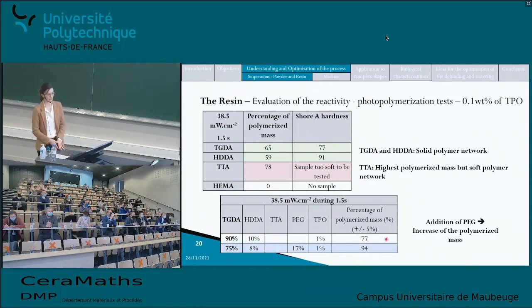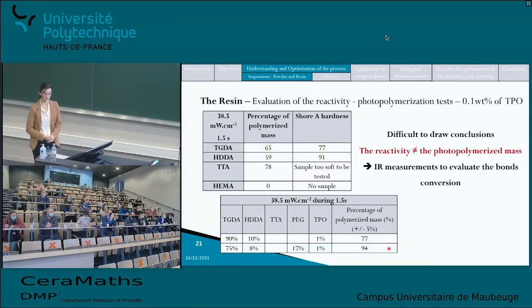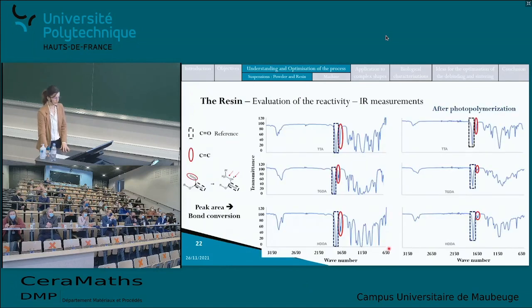However, it is difficult to draw conclusions with this experiment because the reactivity is not exactly equal to the photopolymerized mass. So I added some IR measurements to evaluate the bond conversion and to understand better what happens during the photopolymerization reaction. So I did the IR measurement on 3 of the monomers, the TTA, the TGDA, and the HDDA. So I did some IR spectrum before the photopolymerization and after the photopolymerization. And I evaluated the peak area on 2 bonds, the double bond C=O, which was used as a reference because it is not impacted by the reaction of photopolymerization, and the double bond carbon-carbon, which is impacted because it is converted into a single bond.